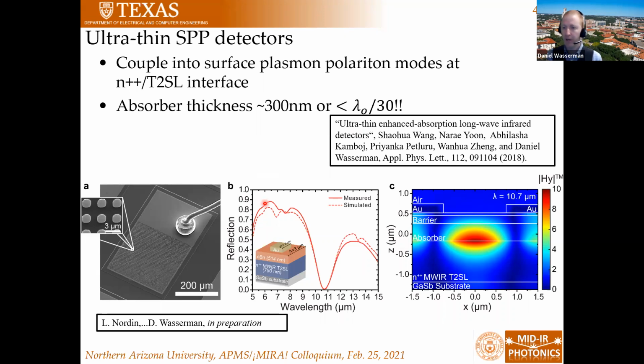What I'm showing here is an SEM and a reflection spectra of a detector that's fabricated that basically consists of a very, very thin NBN detector. This is basically a half micron thick detector, but the absorber region is only 300 nanometers thick. So this is the absorber. We have a barrier and a contact layer. So our absorber is only 300 nanometers thick. And below that we have our plasmonic surface, and above that we have grating couplers. We first proposed this in a paper, I guess 3 years ago now.